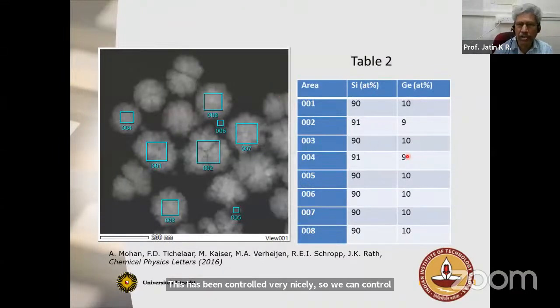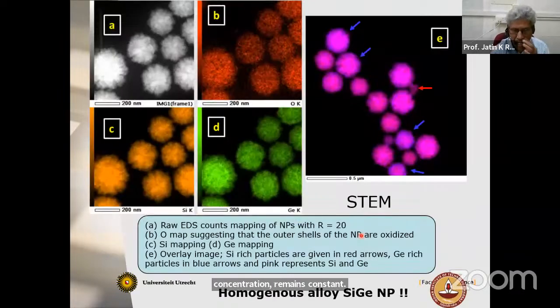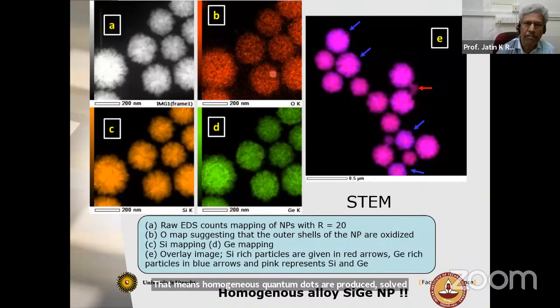And not only that, but at any silane to germane ratio, we found that the germanium to silicon concentration remains constant. That means homogeneous quantum dots are produced throughout. And not only that, but they are mixed up. You can see them, at any place, they are all mixed up. Both silicon and germanium are everywhere.